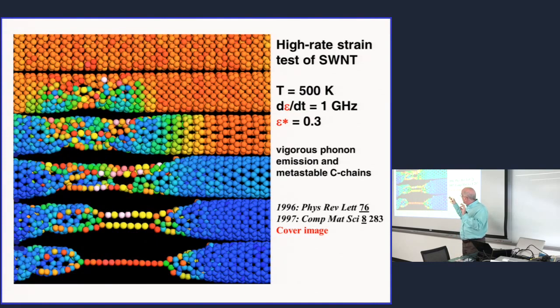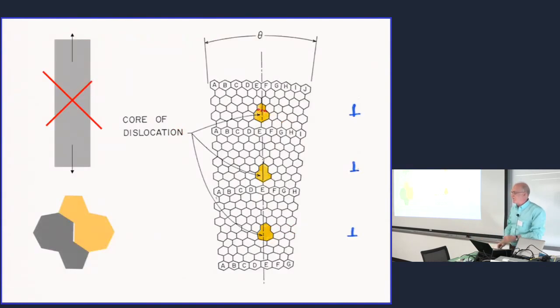What you see here is a perfect lattice, highly strained, and then suddenly it's just an amorphous mass. And mass is not a good scientific message, right? It's just something happens, but you cannot really say what. So the real challenge was to understand what is the very first defect. And molecular dynamics just fails in answering this, at least the way we usually run it. And then we tried to do it a different way, just by thinking and going back to old-fashioned,